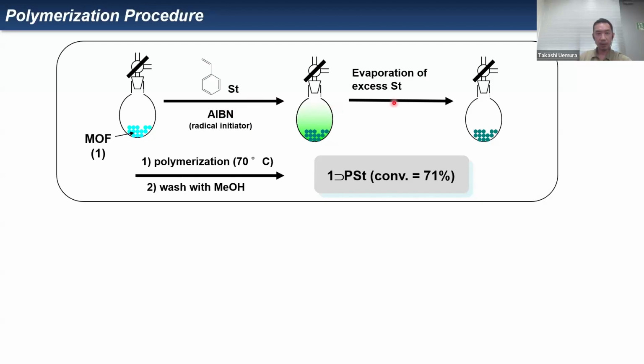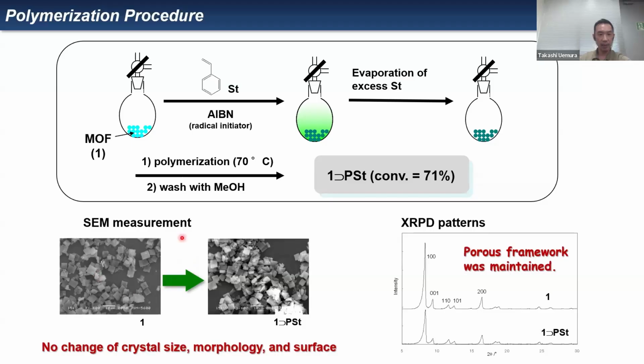And then after the evaporation of the excess amount of styrene outside the host crystal, we perform the polymerization at a higher temperature to obtain this polymer composite. And then for the characterization, after the polymerization, we checked SEM and found no change of the crystal size, morphology, and surface after the polymerization. And then we also checked XRD and found that the porous frameworks were maintained during the polymerization because the XRD pattern was not changed before and after the polymerization.